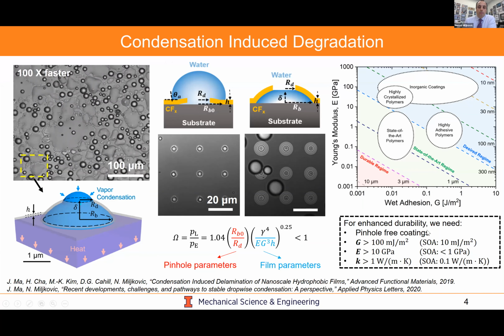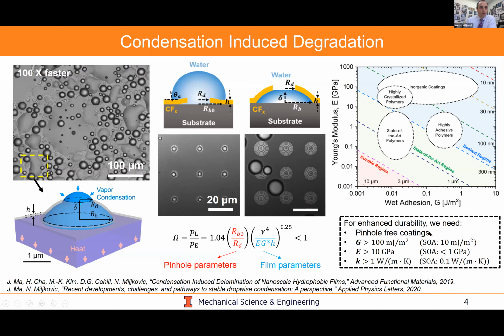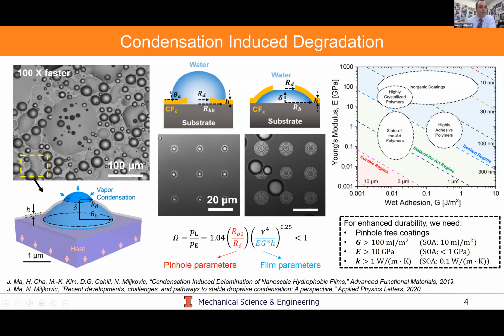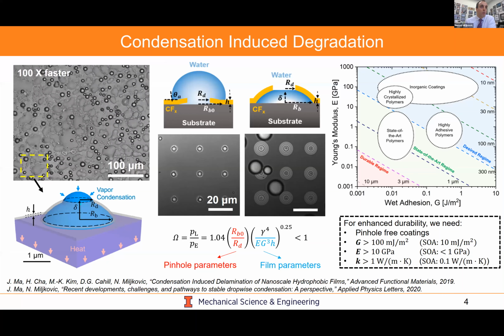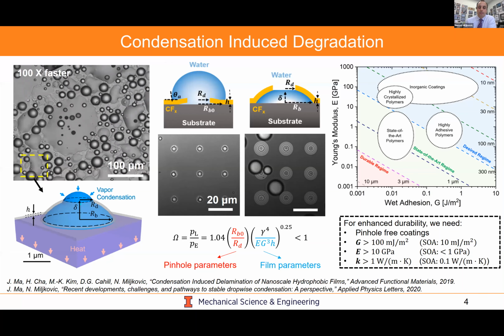And what we find is that for enhanced dropwise condensation, for long-term condensation, we need pinhole-free coatings. We need high wet adhesion, high Young's modulus, or a high thermal conductivity such that our thickness can be elevated. So we could come at this problem from two avenues.